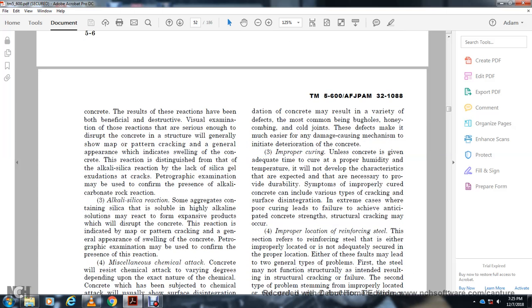Alkali silica reaction. Some aggregates containing silica may dissolve in highly alkaline solutions and react to form a product which disrupts the concrete. The reaction is indicated by map pattern cracking and the general appearance of swelling of the concrete. Petrographic examination may be able to confirm the presence of these reactions.